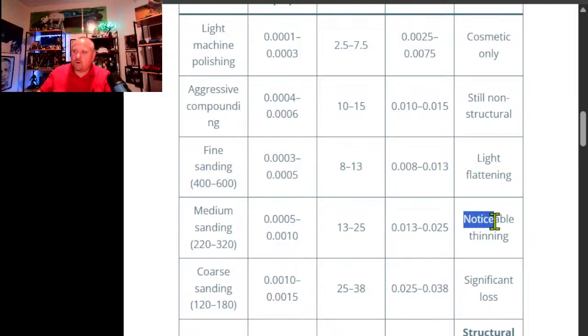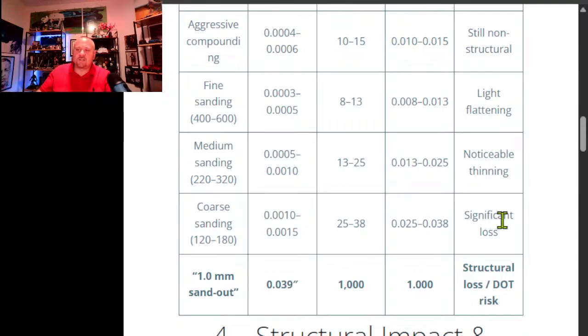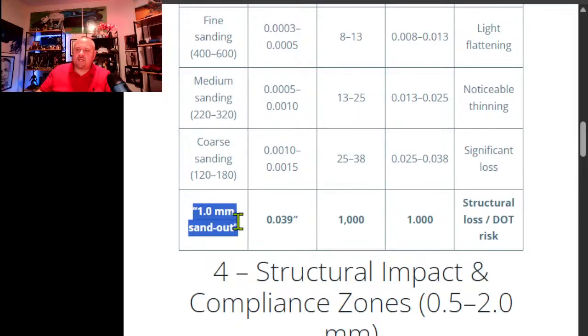Medium sanding, 220 or 320, you already have noticeable thinning. You're already taking off 0.025. As soon as you go to coarse sanding, you're at significant loss. 1 millimeter sand out. What people don't understand is if you have even a 1 millimeter gouge, no telling how long it is, how small it is, a 1 millimeter deep gouge means that what people are doing, in order to get it back out to a mirror, and what you're seeing is aggressive sanding to sand down where that gouge is. Sanding down that aluminum all the way down to at least 1.2 millimeters, because you have to go past that. You have to go past the depth of that gouge, and you have to take that material down.